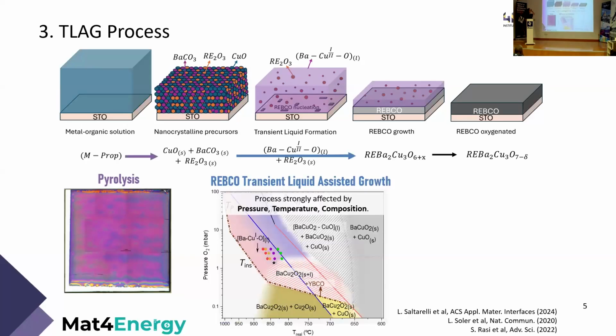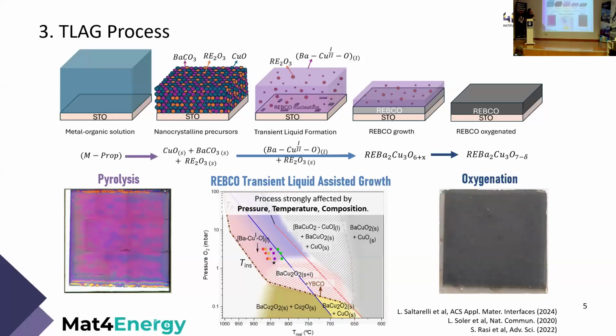Then, in the second heat treatment, is when the REBCO crystal actually forms, and through the formation also of a transient liquid of barium and copper. This process is the real key that we are trying to investigate the most, since it is highly dependent on pressure, temperature, and composition. Finally, we also perform an oxygenation process in which we convert the REBCO film into a real superconducting material.